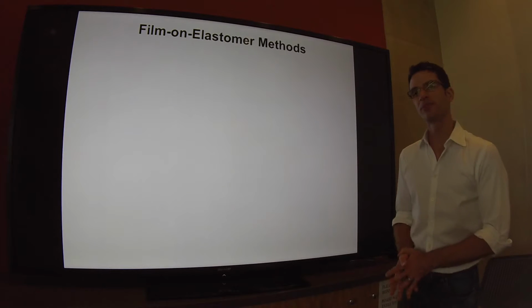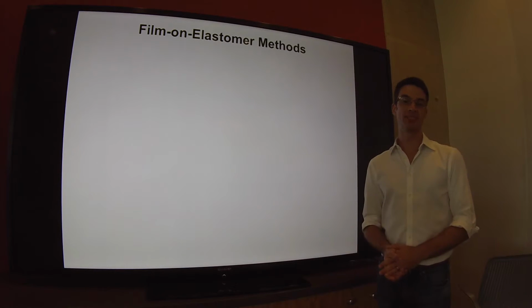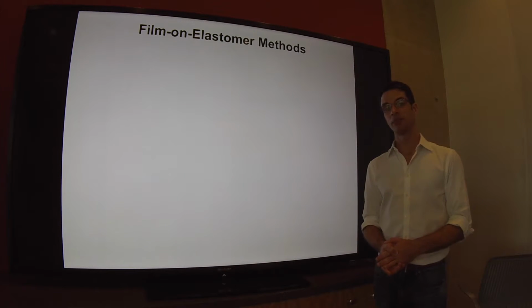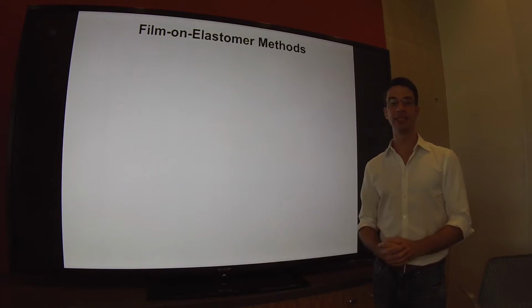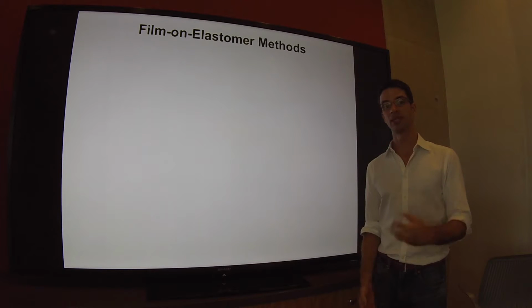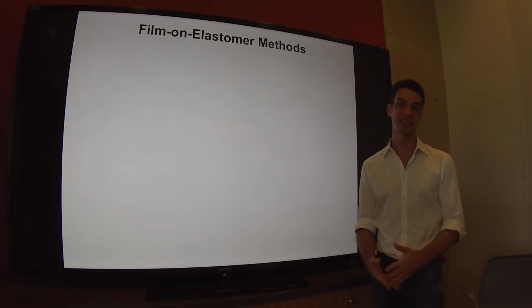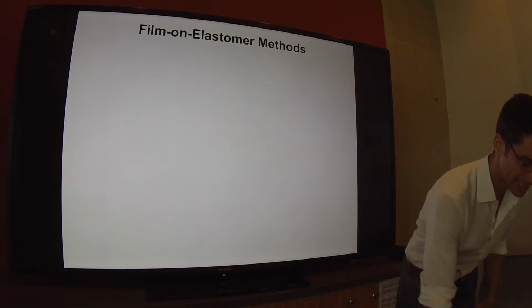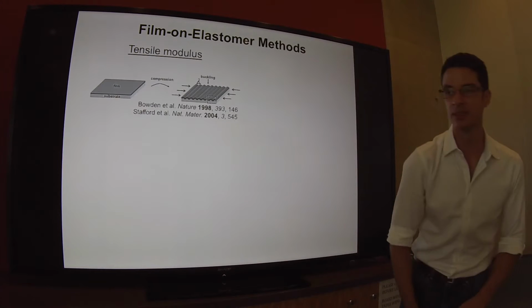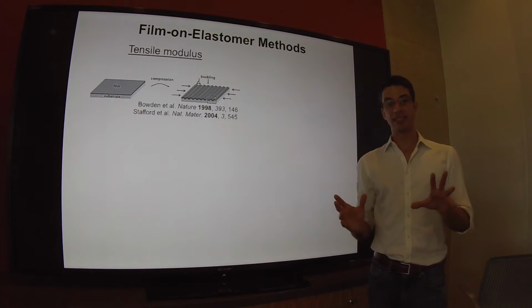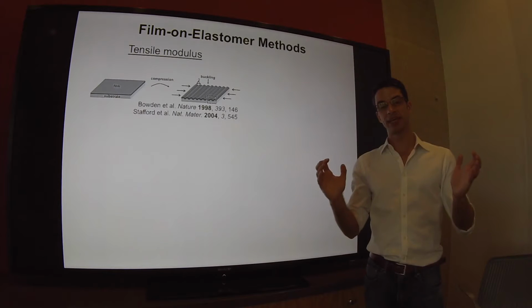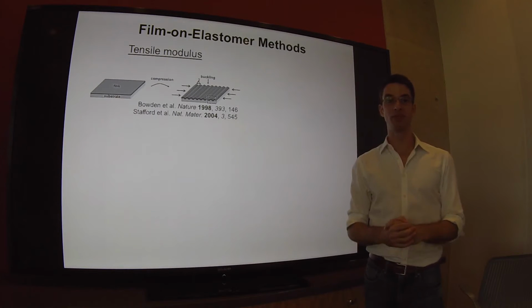So one of the major challenges associated with measuring the mechanical properties of these materials is that they are almost always used in thin film forms. So films that are less than 200 nanometers thick, or at least less than half a micron. So it's very difficult to get the mechanical behavior from a traditional pull test.